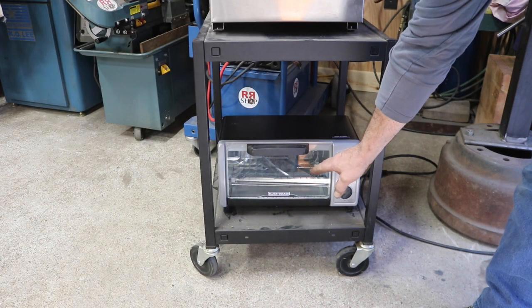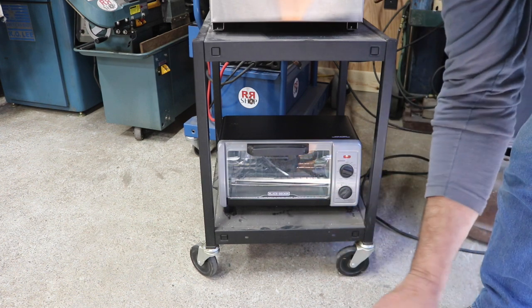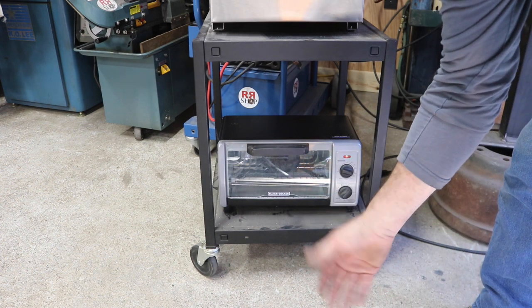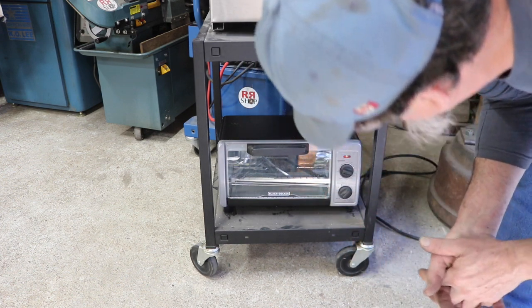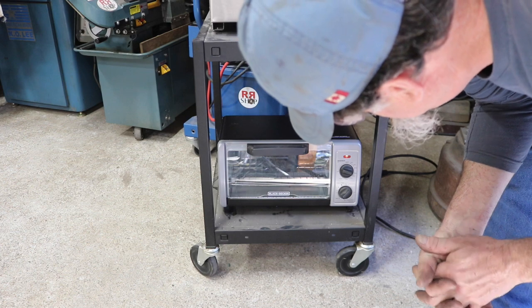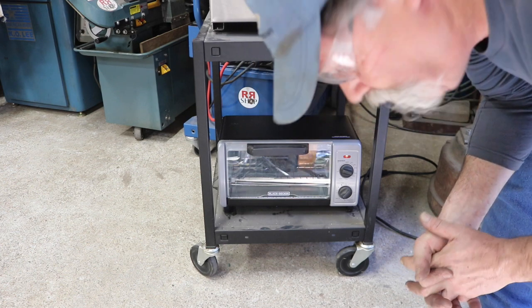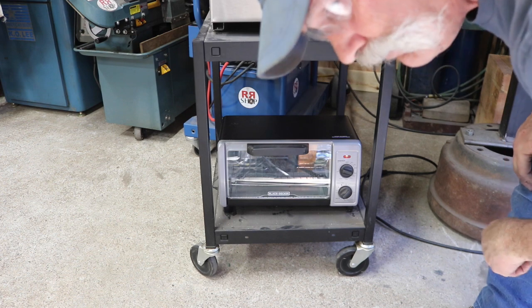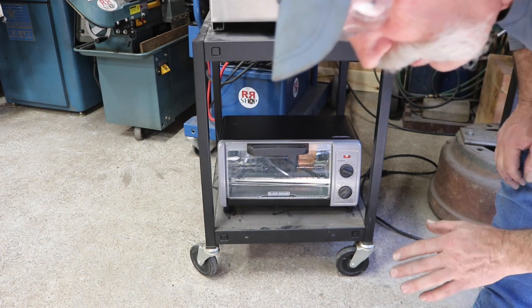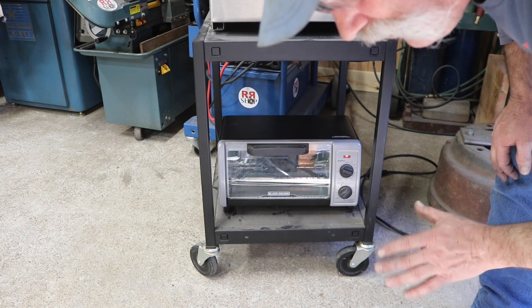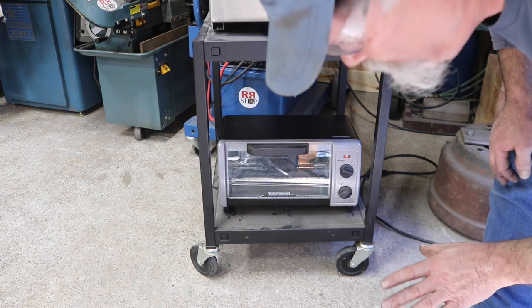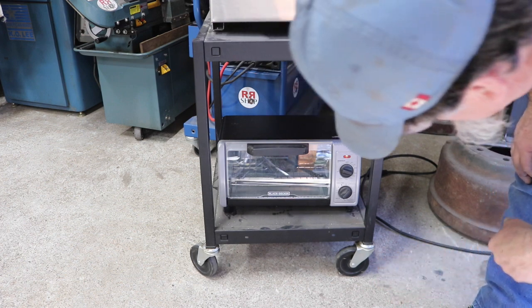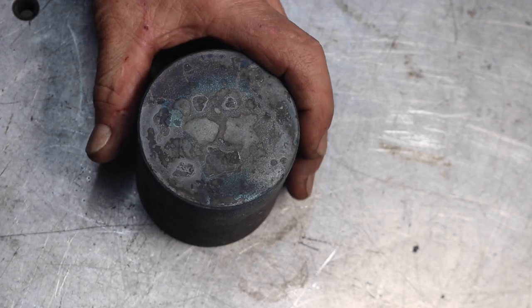Right into the 350 degree oven. We've got it down to around 280 or so on the outside at least and put it right into tempering. We'll leave it in there for a few hours and hopefully we came out nice and hard on the faces. That's all I'm concerned about. That's why I dipped it in the faces first to try to get those hardest.